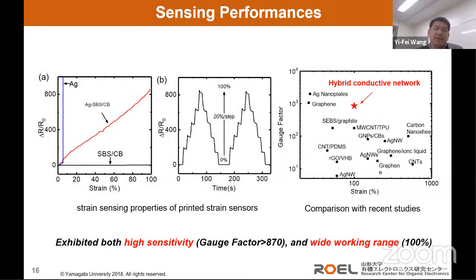Here we show the performance of our developed sensor in figure A, and we can see that if we only use the brittle layer, like a metal film, the device will fail to conduct at a very low strain of about 5%. And if we use only the stretchable conductor, of course we can go to very high stretchability, but the sensitivity is quite low. When we use our newly developed brittle-stretchable conductive network, we can see our sensor achieved both high sensitivity and a wide sensing range. And this sensor also shows very good linearity and quite low hysteresis, as shown in figure B.